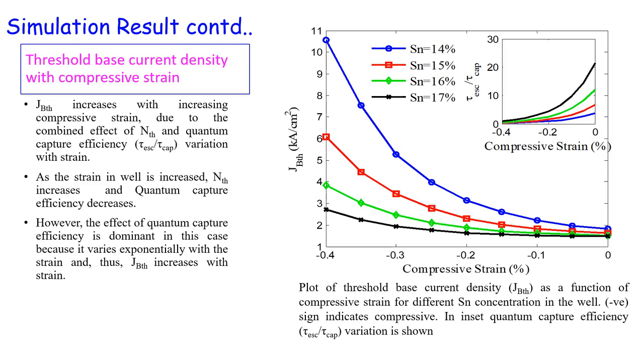This decrease in quantum capture efficiency is mainly due to the effective band offset variation with strain. The reduction in quantum capture efficiency means fewer carriers are captured into the well, so a higher base current density J_Bth is required to achieve the threshold condition. The effect of quantum capture efficiency is dominant in this case because it varies exponentially with strain, and thus J_Bth increases with increasing strain.